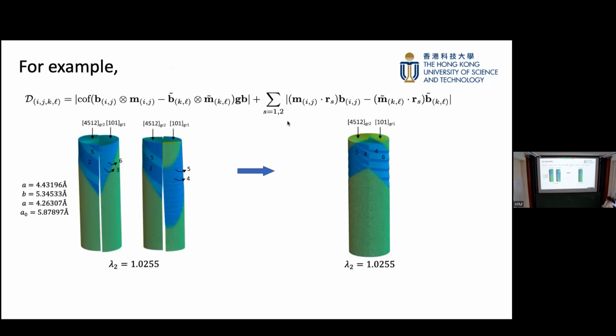So this is the result. Instead of those types of things for the single crystal crystallographic compatibility, we find a different twin laminate, which is 5, 4, 4, 6, that satisfies this and makes it a minimum, and that corresponds to this metric in very small values. It's not 0, so that means there is still some misfit, but the misfit has been minimized.